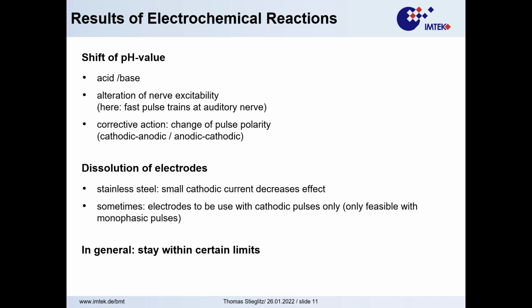One measurement method that has been established is that you stimulate electrodes in vitro in beakers in salt water, billions of times, and then you investigate the water. Not only the electrode, but you investigate the water to see if there are solvents in there. Since the detection limit of most of the machines is under the amount of platinum that might have been dissolved, you play some tricks. So you evaporate the water: I have now 10 milliliters, I cook that down to 1 milliliter, that's a factor of 10, and I go to whatever mass spectrometer. If I find platinum, then I have to divide that concentration by a factor of 10 or something like what you did before, and then you can find that out. That's established worldwide as a method to check whether I have dissolution or not.